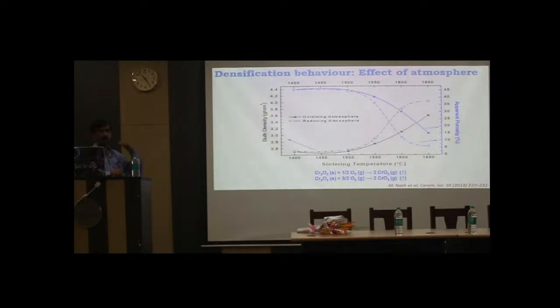Because when you sinter this material in oxidizing atmosphere, the Cr2O3 has a tendency to form higher valent oxides, the tetravalent and hexavalent. And both of these oxides, CrO2 and CrO3, have a high vapor pressure. Since it has a high vapor pressure, at this temperature it evaporates from the system, leaving behind the pores. That's why it is difficult to sinter the material in oxidizing atmosphere. But if you can maintain an oxygen deficient atmosphere, either reducing, neutral or inert atmosphere, then you can easily densify this material.